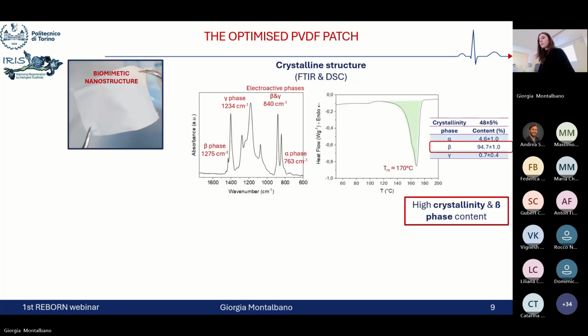native tissue. And then the physical-chemical characterization combined with thermal analysis led to the definition of the overall crystalline content of the polymer, where we registered the highest amount of beta phase compared to the other crystalline phases, with a value higher than 90% in the final content. So once again, confirming the effective synergistic effect that the combination of the electrical pulling and the mechanical stretching can have during the electrospinning process.